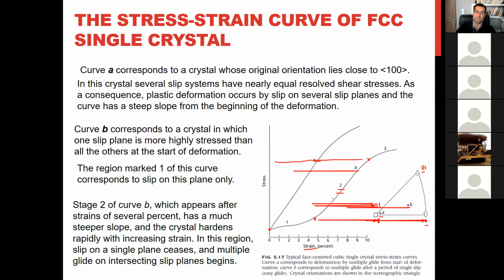So in FCC crystals, for a single crystal stress strain curve, we can see two types of curves. This curve is when several equivalent slip systems are activated, and we have strain hardening from the beginning. So far, we don't know why. I am going to explain it. But if we manage to apply load in a direction that activates just one slip system, similar to HCP like magnesium, we can see the easy glide part. And after a while of deformation, we will see strain hardening. And again, we see a decrease of that strain hardening. Okay?